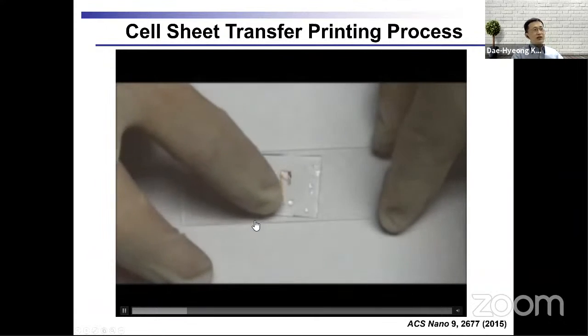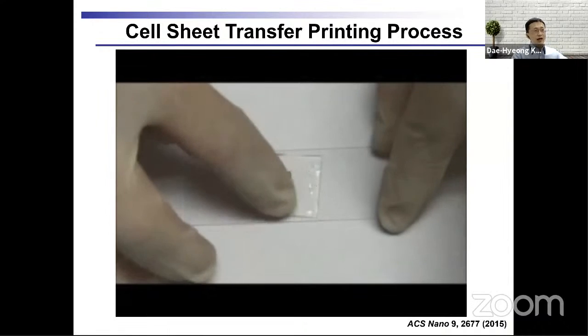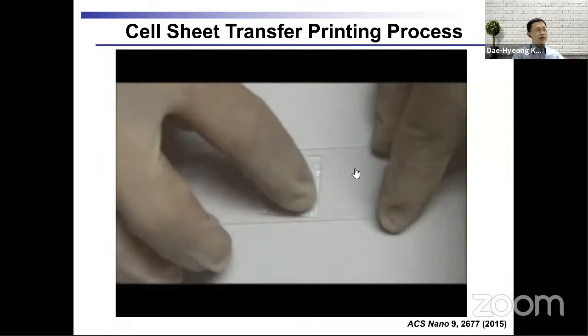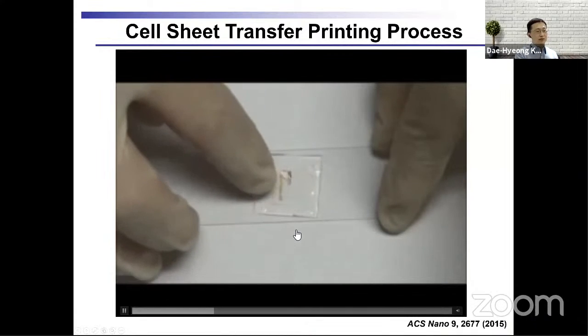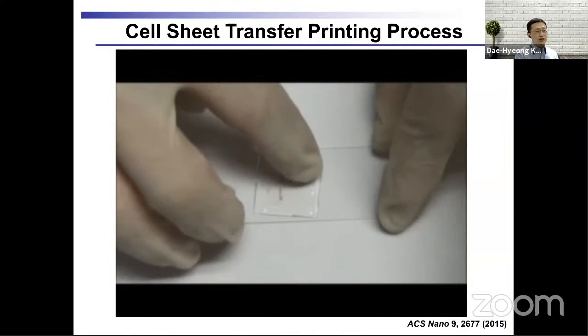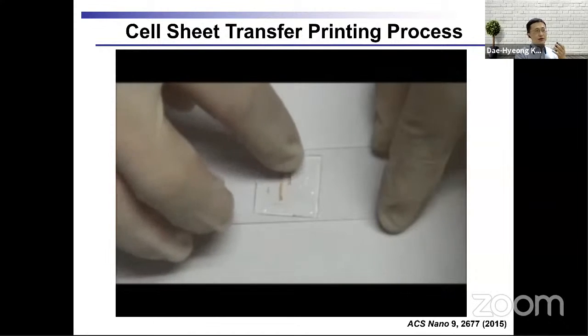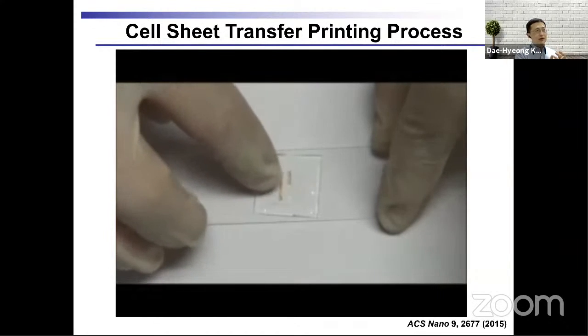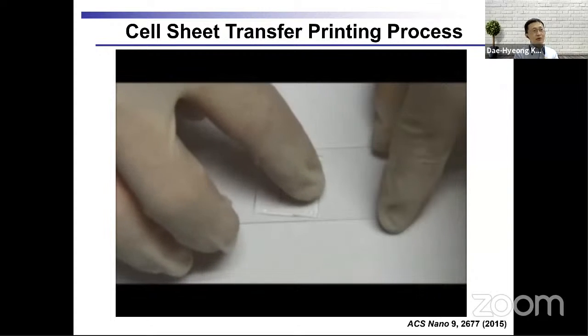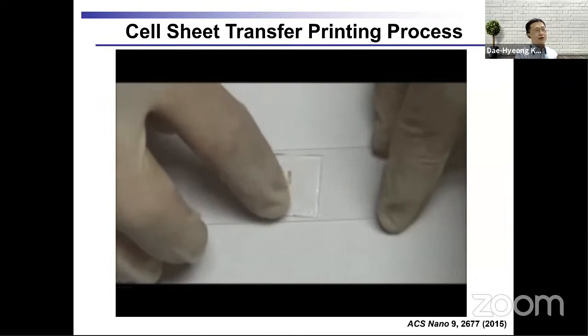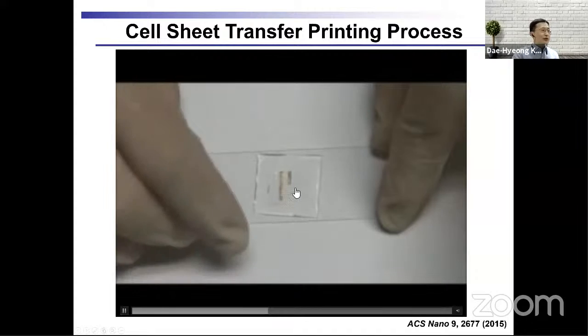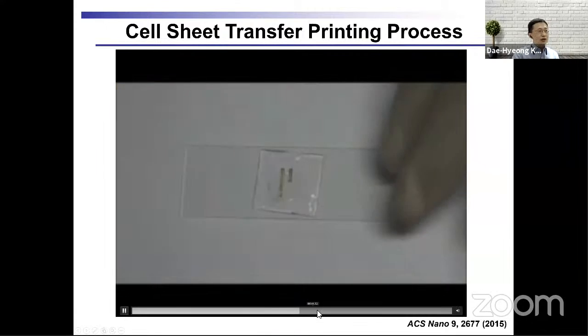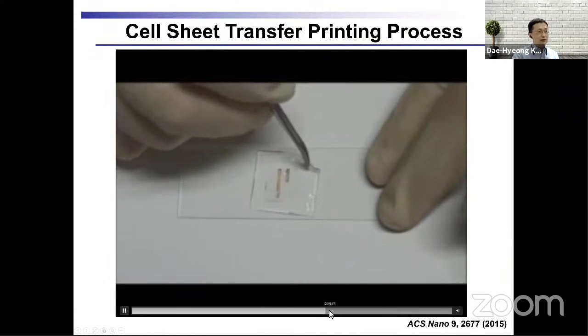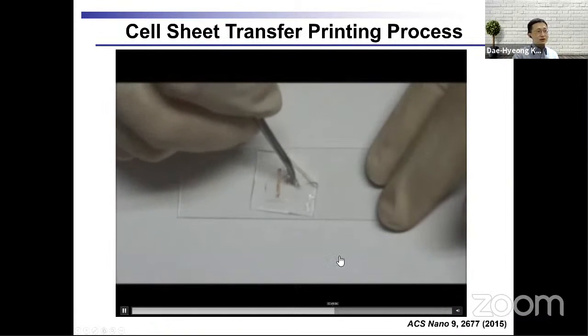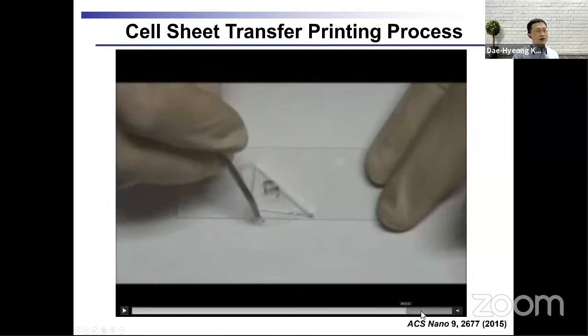Actually, transfer printing yield to the animal tissue is higher than to the glass substrate, because animal tissue typically has many amine groups, so good covalent bonding and hydrogen bonding can be made between the cell sheet and the tissue. After making contact, we wait roughly 90 seconds and peel the PDMS stamp. Then we can transfer print the cell sheet.